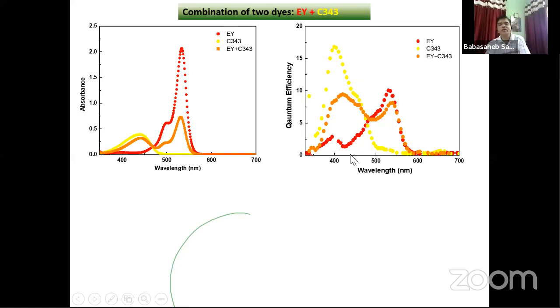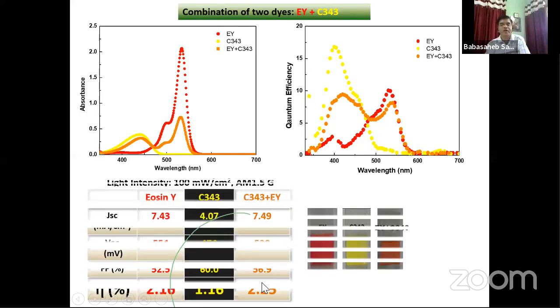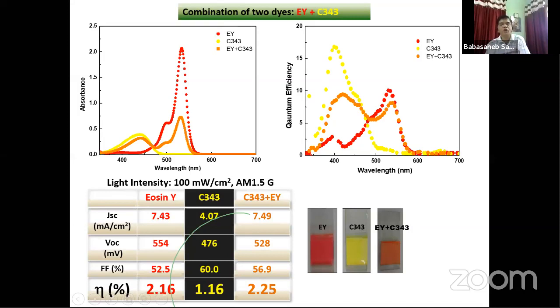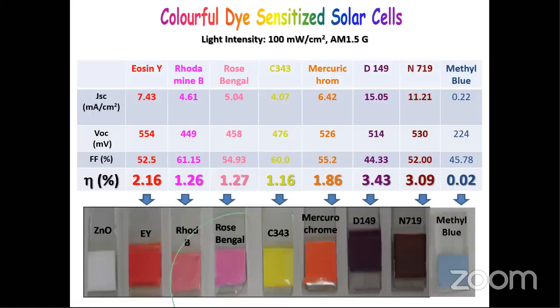Yes, it is the quantum efficiency against the wavelength. This is for the completed device. Here you can see that this completed device also covers both parts of the solar spectrum, from the yellow as well as from the red dye. So this is the efficiency of the cocktail dye, which shows an enhancement in efficiency, not so high, but better than eosin Y dye, reaching 2.25% just by mixing two dyes. Not only this one, we have tried different dyes like rose bengal, rhodamine B, mercurochrome, D149, and N719, adsorbed on the zinc oxide.